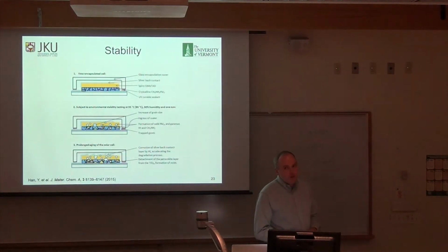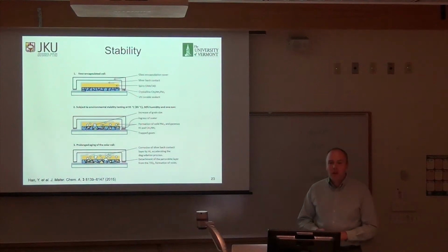Another critical issue is the stability of these cells. If you make this perovskite solar cell and encapsulate it extremely well, then it's fine—it lasts pretty well. But if any water vapor gets in, it attacks the perovskite and releases hydrogen iodide gas, which bubbles out. That, in turn, attacks the electrode, which makes the electrodes fall off, which exposes more of the surface to the water vapor—a self-catalyzing reaction. These things die very quickly if there's any exposure to ambient air. That's a real problem.